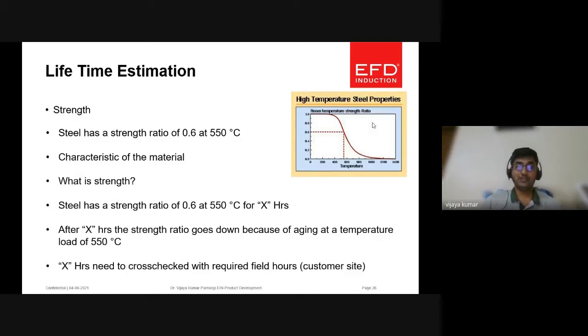Okay, and a little bit on the strength. Steel has a strength ratio of 0.6 at 550 degrees centigrade. Slowly, with temperature it also changes. At room temperature, if you consider the strength as 1, then as the temperature increases, the strength goes down.